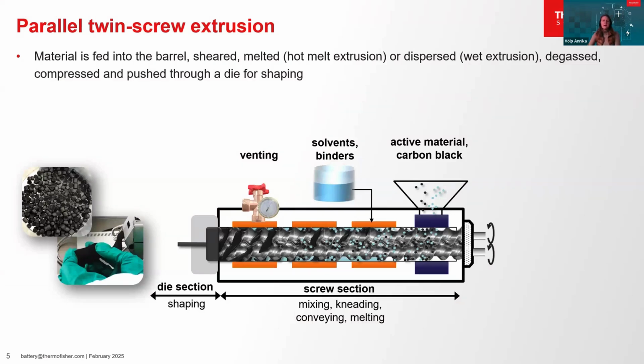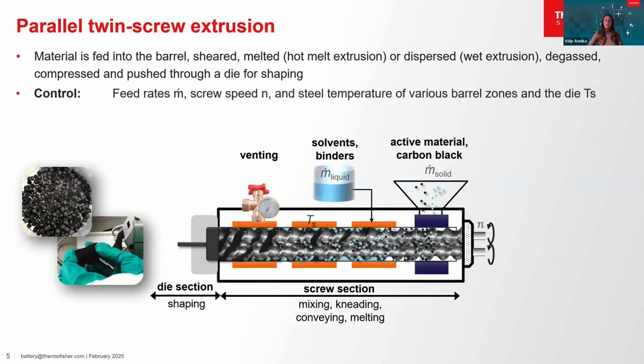In general, the task of the parallel twin screw extruder is to apply thermal and mechanical energy to create a dispersion and shape it. Solid materials such as the anode or cathode active material and carbon black are fed into the extruder barrel and sheared. During melt extrusion, a polymeric binder is added, which is melted in the heated twin screw barrel. In wet extrusion, solvents and binders are added to the barrel via a liquid feeding system. All materials are mixed, sheared, and compacted and pushed through a die.